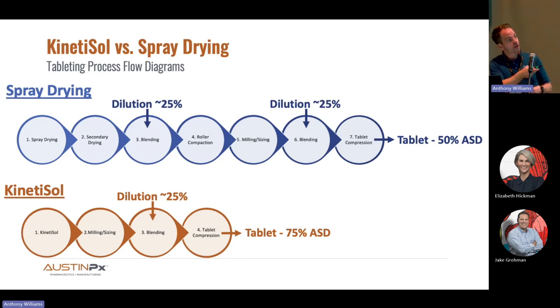Then coming out of roller compaction, you've got a sizing step, followed by additional dilution, adding external phase excipients headed into tablet compression. So from what we've seen with spray dry comparators that we've gone head to head with, tablets, as a midpoint, contain about 50% of the spray dry dispersion. Whereas with KinetiSol, we've eliminated 3 of these steps. There's no need for secondary drying, blending, and roller compaction prior to tableting. We come out of KinetiSol, go into a hammer milling step, a milling sizing step, and then adding the external phase excipients. Typically, 25% is all that's necessary to achieve a tablet with acceptable tensile strength and disintegration properties.